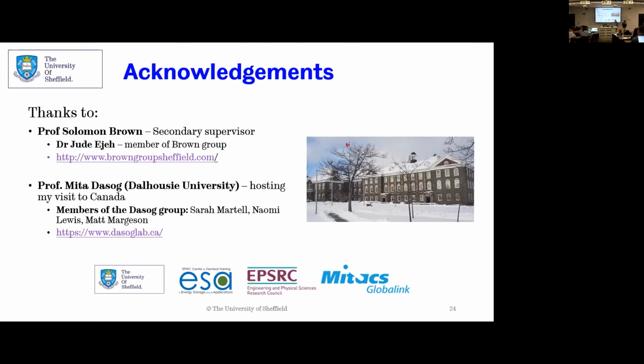And that's something that I will study, hopefully in a postdoc position after this. It's going to be difficult to control one thing at a time, but the key thing with the magnesium reduction is that you can use even sand or old glass bottles, and people have done this in literature. So it can make porous silicon from non-porous sources. So you don't necessarily have to use a really expensive silica feedstock for this.